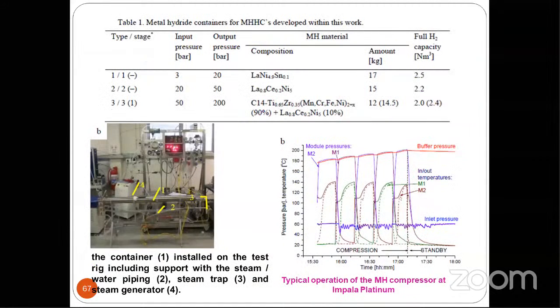I'll show here. We have 3 stages to compress the hydrogen. In the first stage we use a different composition, and we can compress the hydrogen from 3 bar up to 20 bar. Then in the second stage, again using a different material, we can compress 20 bar to 50 bar. Again in the third stage, 50 bar to 200 bar, using again different materials, because these materials are chosen based on their PCT, pressure versus temperature and concentration, that I have shown earlier.